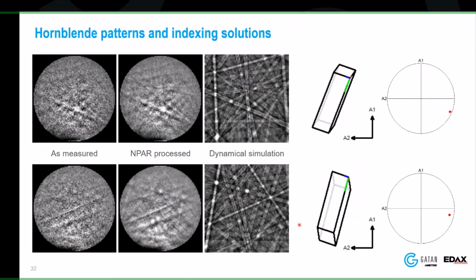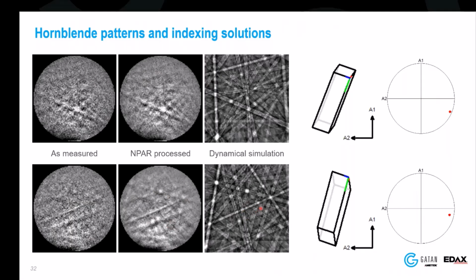So garnet is pretty straightforward. This is honestly the one I'm a little more impressed by. Here's a hornblende. Hornblende's tricky. Again, here's the pattern as measured. In a super low symmetry material, we get very busy Kikuchi patterns in general. We can see there are hints of lines basically all over the place. We run it through NPAR, and I can start to see some of the information a little bit better. And of course, I compare it to the orientation solution that we get, and we can see that we do a pretty good job here.